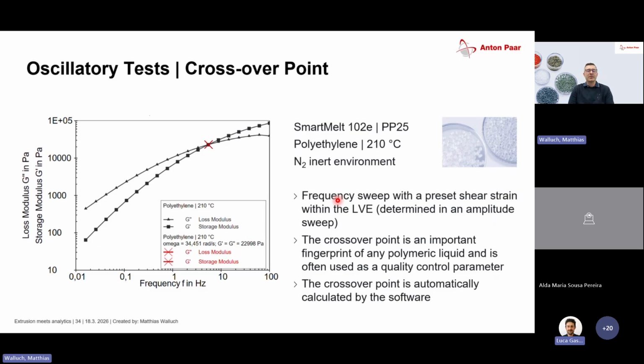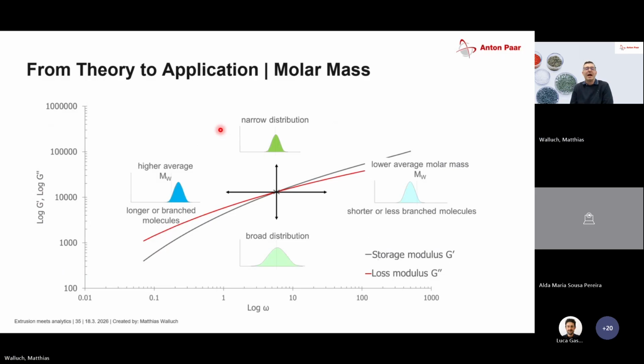Okay, now let's go to some additional information that they get out of oscillatory tests. In this case, the crossover point, which you only get because you know G' and G''. And this is very unique for every material, and it's also dependent on the temperature and the combination. And what does this crossover point tell us? It tells us basically, again, something about the inner structure of the polymer.